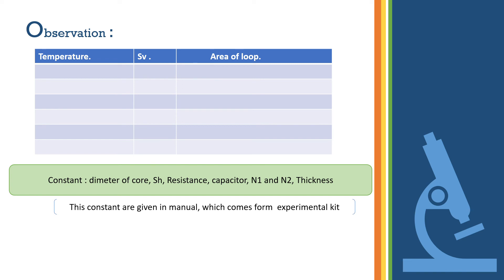Then we manually increase the temperature of the oven in which the ferrite iron core is placed. As the temperature increases, the hysteresis loops are decreasing in area.